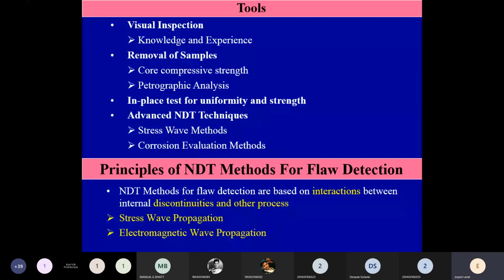Then we go for some extraction of samples. Those samples can be used for determining the compressive strength, where we take concrete cores. The same concrete cores can be taken to determine other mechanical properties like modulus of elasticity, Poisson's ratio, split tensile strength, shrinkage parameters, etc. Many times in case of dams, creep is also important, so we conduct creep tests also on the samples extracted from the structure.